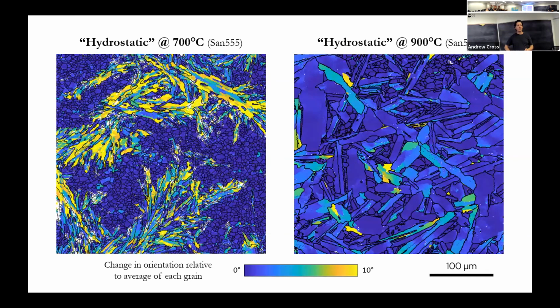Now, if we look at our misorientation map for these two samples, again, we've got a fair amount of crystal lattice bending at 900 C, but it looks really crazy when we go to 700 C. There's lots of internal deformation here, and these coesite needles that are nucleating are really being bent up, and they're accumulating a lot of defects.